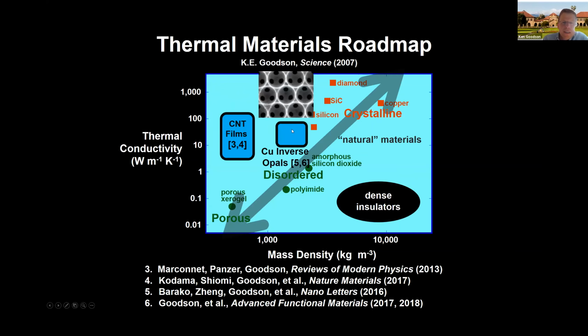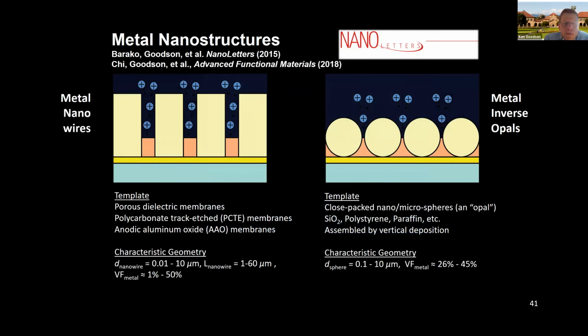And for high conductivity in porous media, you can either use carbon nanotubes. We did some work on that in the early 2012, 13, 14. Or you can work with porous metals that are highly systematic in their structure. And that's something we've been working on more recently. So how do you make a metal nanostructure? And here we're really borrowing from the photonics community, which has made metamaterials, and also ceramic and other materials, metamaterials that allow you to modify the transport of photons.